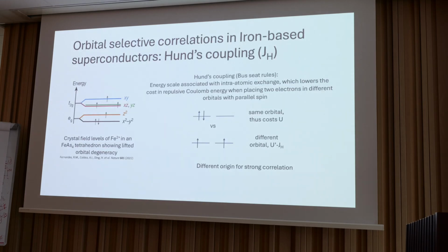Now we can talk about some of the normal state. As the last speaker talked about, there are these orbital selective correlations in iron-based superconductors due to Hund's coupling. I showed this figure earlier, but once you have this crystal field splitting that lifts the degeneracy of these bands, then you have this competition of how to fill the no longer degenerate bands. And Hund's coupling comes in, which is basically the energy scale associated with intra-atomic exchange. So you save JH by placing electrons in different orbitals in a high spin configuration as opposed to in the same orbital. So this can act as a different origin for strong correlation.